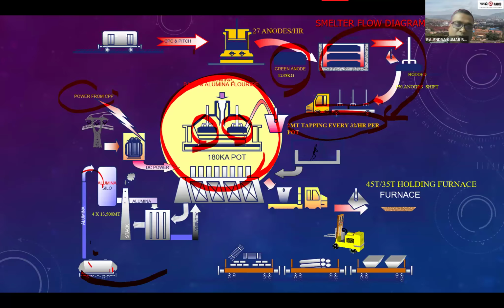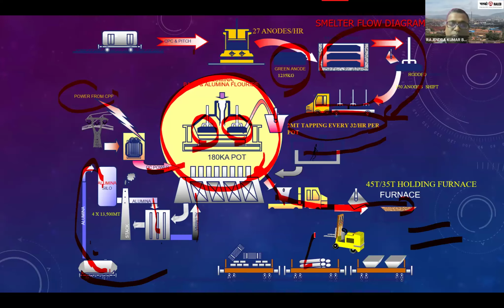We are transporting this alumina through rake, and we are storing it there. There are 4 numbers of alumina silo, its capacity 13,000 metric ton. From the silo, we are putting alumina to the pot. We are adding DC power. We are adding the anodes from the rodding shop, and we are getting the molten metal. Then molten metal goes to the furnace. In the furnace, we are getting different types of material: billets, slabs, and wire rods.